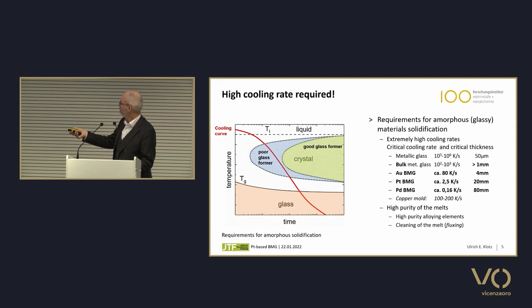And just for comparison, if you quench into a copper mold, you can reach about 100 to 200 Kelvin per second as a cooling rate. So this is required for gold bulk metallic glasses, but for platinum, we hope to also do this by investment casting. What is important is to have a high purity of the melt, because all impurities will act as nucleation sites for the crystals, and so reduce the critical thickness that you can reach during quenching.